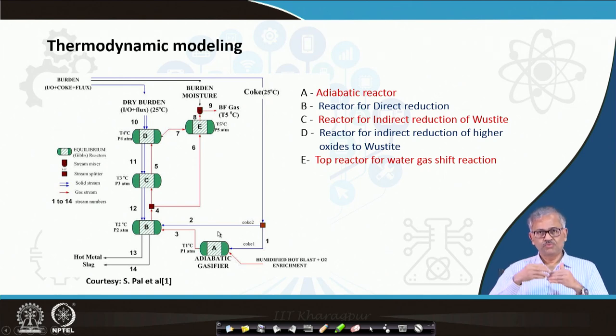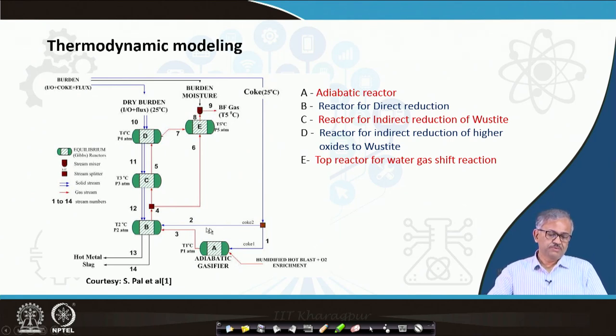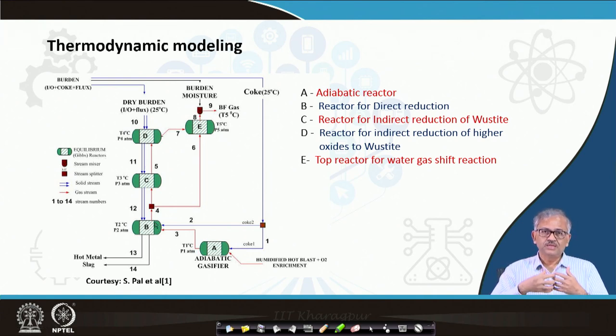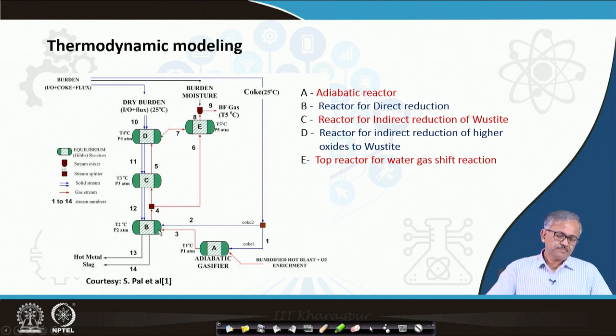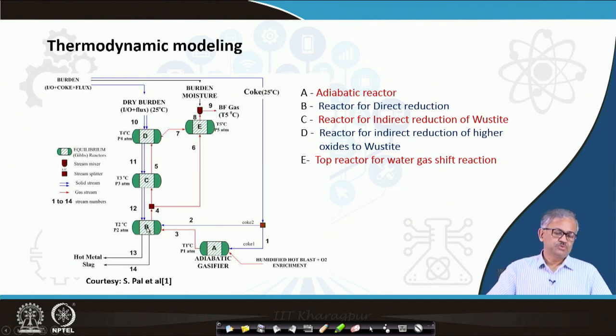A certain amount of coke will participate in the direct reduction — I am splitting the coke here. How much coke to give for direct reduction has to be estimated by an iterative method. Some amount of direct reduction takes place; basically here you will get wüstite only. A part of the wüstite will be directly reduced and part will be reduced by the CO gas — that is indirect reduction — and some direct reduction will be there.